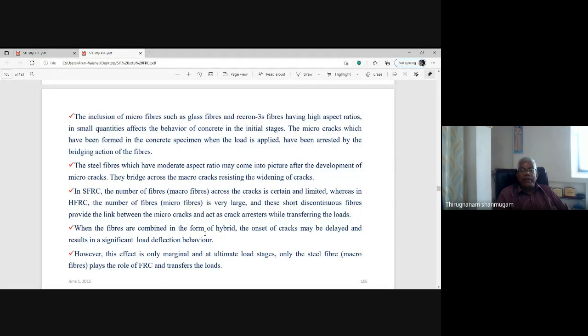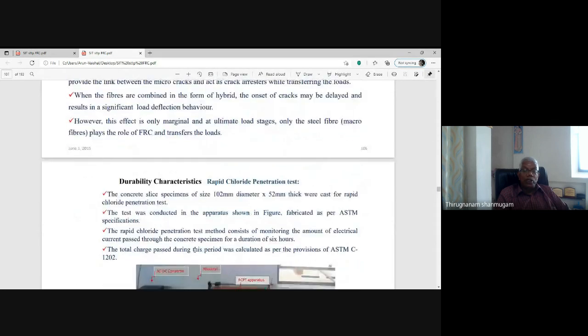When the fibers are combined in the form of hybrid, the onset of cracks may be delayed and result in a significant load deflection behaviour. However, this effect is only marginal at ultimate load stages. Only the steel fiber plays the role of FRC and transfers all the loads.